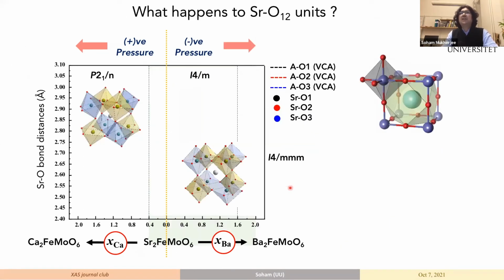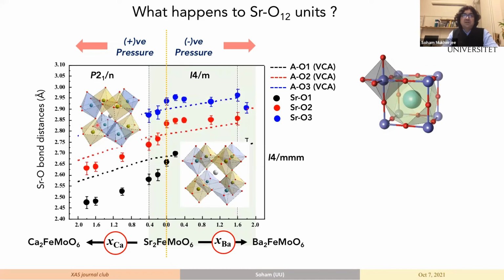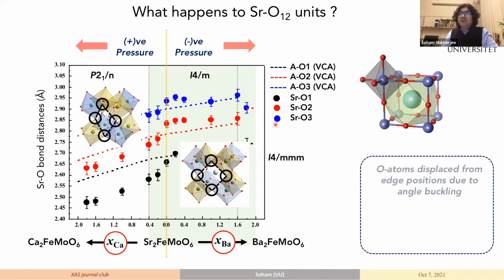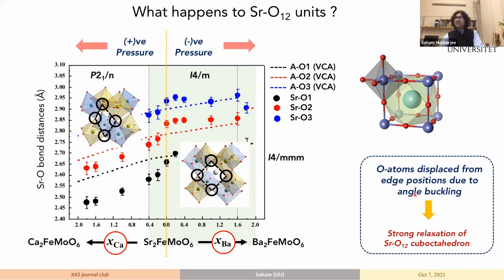So when we stitch these two together, we see that, okay, we can now understand what is going on with the SrO12 units. When you have the master plot, you'll see that there is much stronger relaxation on the SrO12 cuboctahedra. And this is because of the rotation of the individual octahedral units, because these are the atoms which are now moving apart from each other. And now it creates a lot of distortion. But here it increases in a very linear fashion. And then it hence scales perfectly with the chemical pressure line. So this buckling of the angles defines strong relaxation of the SrO12 cuboctahedra, which does not happen when you dope strontium with barium, the negative chemical pressure regime.